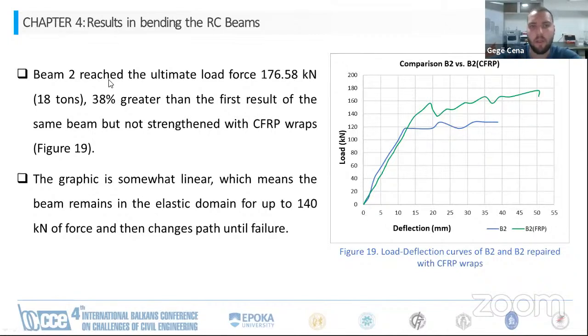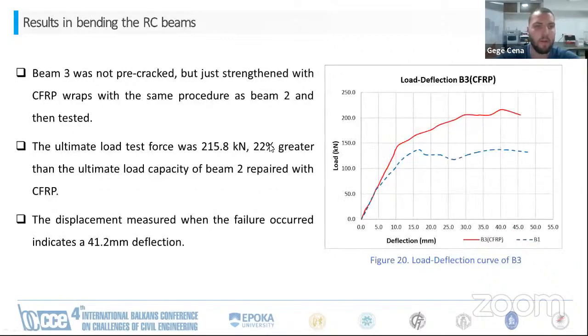now these are the results in the bending of reinforced concrete beams. Beam 2 reached an ultimate load force of 176 kilonewtons, which is 38% greater than the first result of the same beam, but not strengthened with CFRP wraps. Beam 3 was not pre-cracked, but just strengthened with CFRP wraps, with the same procedure as beam 2, and then was tested. The ultimate load test force was 215 kilonewtons. That is 22% greater than the ultimate load capacity of beam 2 that was repaired with CFRP wraps.